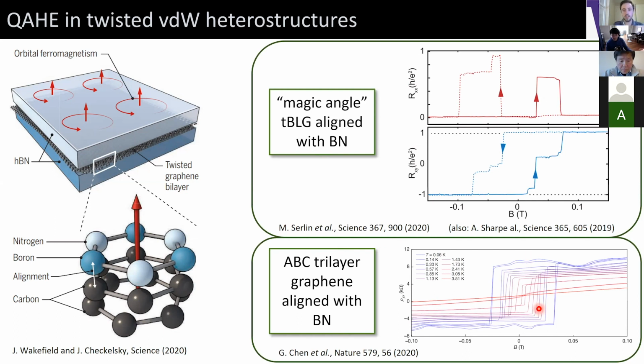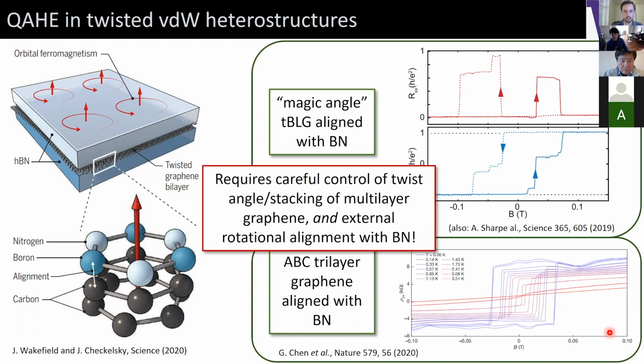So in fact, these systems are not only quantum anomalous Hall states, but they also have different and perhaps even tunable Chern numbers. The annoyance here is that this requires careful control of the twist angle and/or stacking configuration of the multilayer graphene. And further, you have to externally rotationally align with the boron nitride. So these samples are remarkably difficult to make, and there's really only been a couple of each one of these that have ever been successfully fabricated.